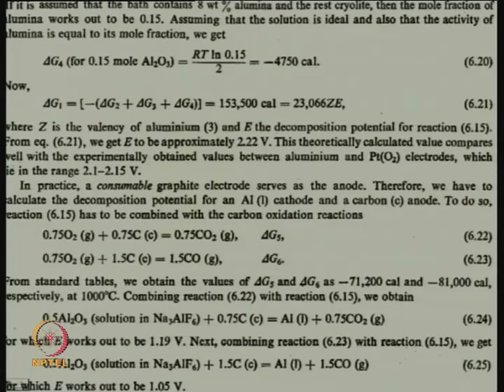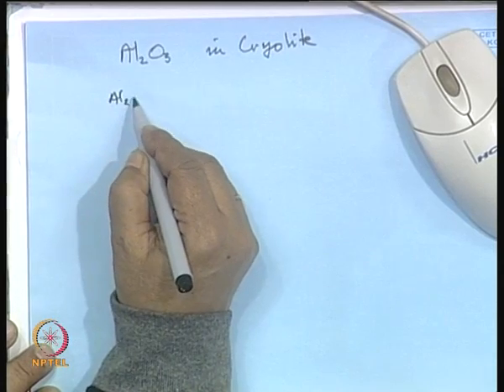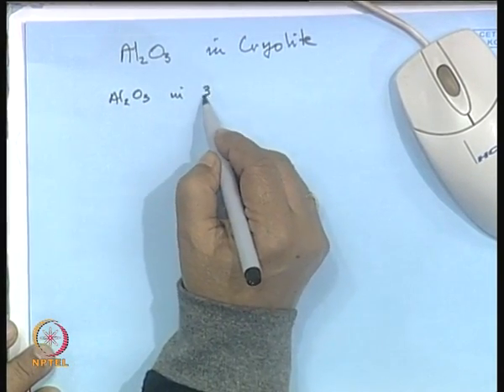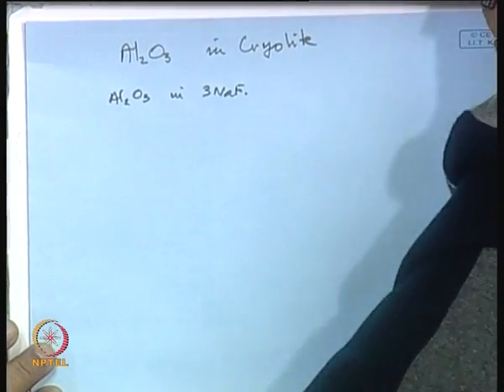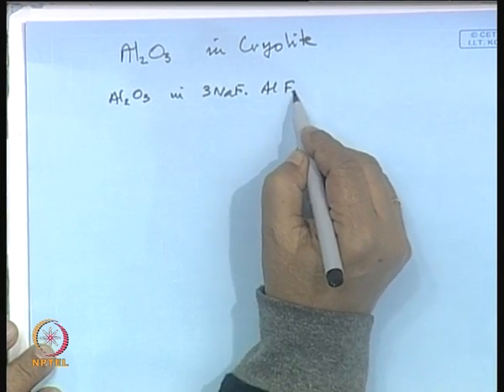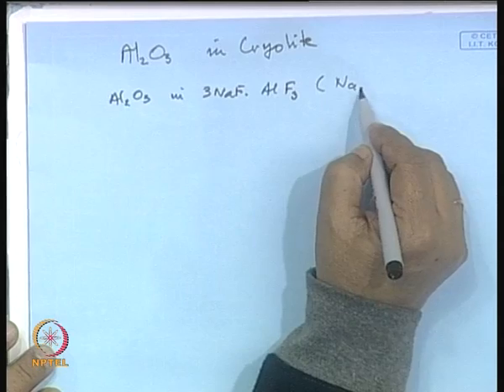Now, there is a little bit of error in this calculation, because we are assuming that when the mole fraction for 8% alumina is 0.15, the activity is equal to 0.15. Actually, this is not quite so. You go back to my discussions on the Temkin model for fused salts. If we consider Al2O3 in 3NaF into AlF3, that is Na3AlF6.